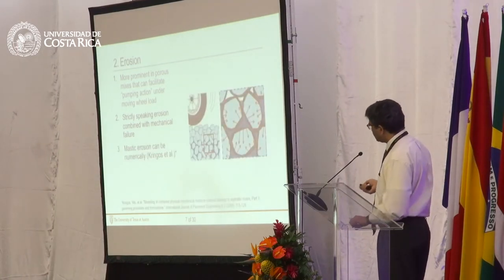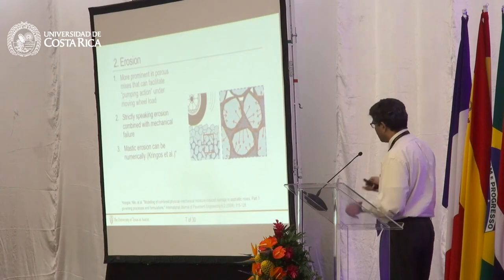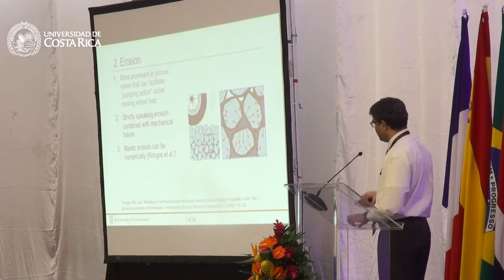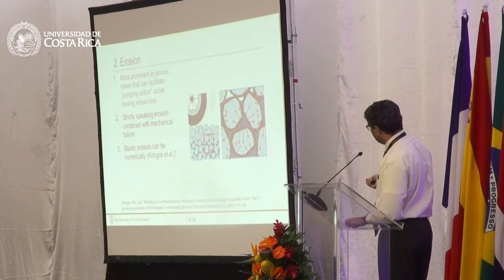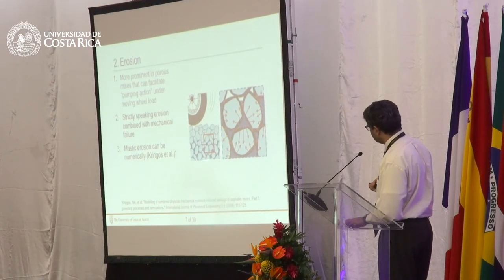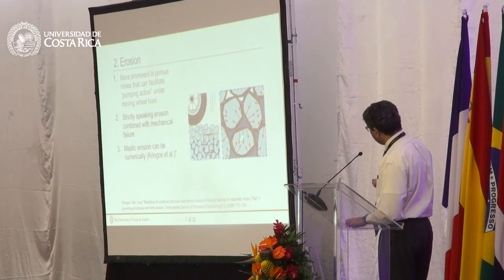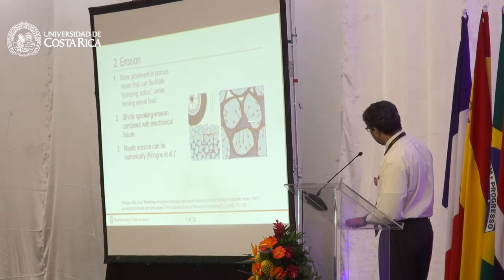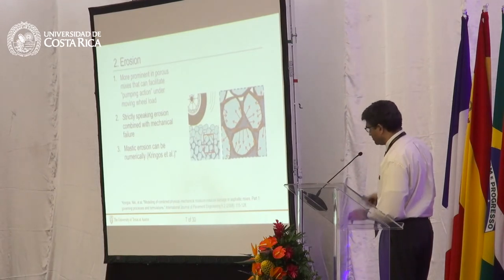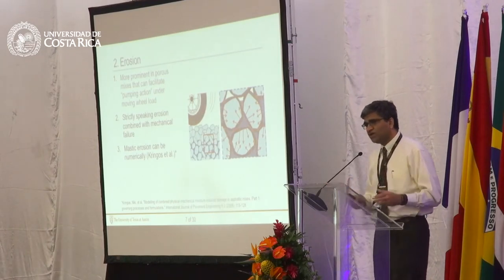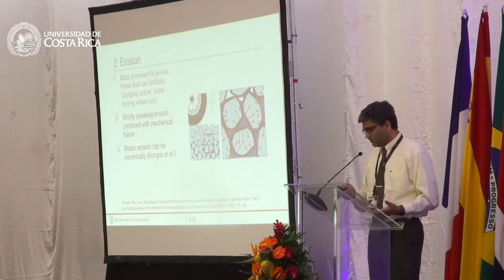And there was an interesting study put together at the same time when all of these other studies with moisture damage were going on, that looked at modeling that erosion. Basically, you would have this open graded friction course or permeable friction course. You would have moisture, and you could model a wheel load and the rate at which moisture would try to escape from that structure and calculate the amount of damage it could do.